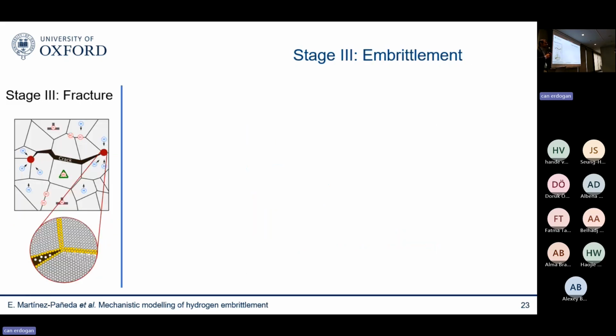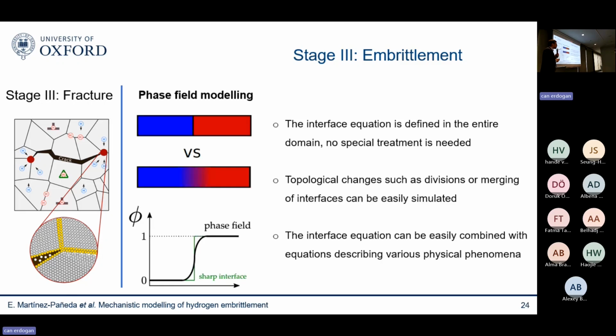Okay, so now we are moving to the embrittlement part. So we know where the hydrogen is distributed within the component, and we also know where the hydrogen is distributed within the microstructure, which relies on those binding energies that I told you before. So now what happens with the cracking process? And here, I think one of the challenges is, there's two types of challenges in trying to predict when hydrogen embrittlement occurs. One is a physical challenge, so what is actually hydrogen doing that facilitates the nucleation and growth of cracks?